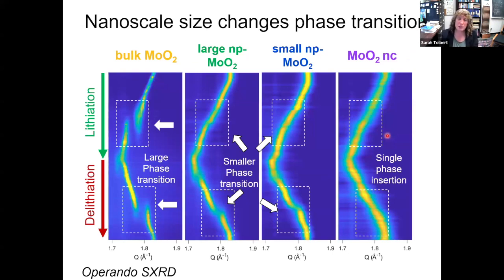So this is a technique that chemists commonly use to determine the structure of solid materials. And we have many different scattering peaks. I'm showing just one of those peaks here. And we're going to trace it as the material is charged. So we see this peak shifts, and then all of a sudden it jumps to a new position. And that is a phase transition. This is on charge, and then it jumps again on discharge. This is the bulk. As we get smaller, the size of that jump gets smaller and smaller until in the smallest size sample, there is no jump at all. So we have converted a phase transition to a solid solution with size.